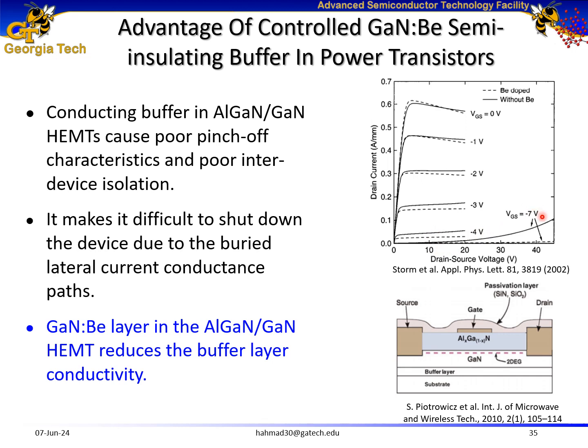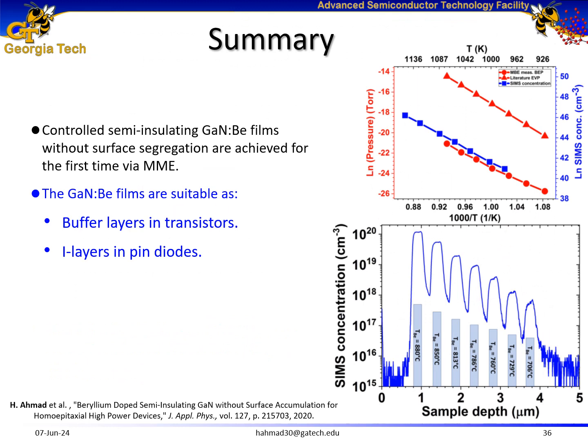Semi-insulating controlled beryllium-doped gallium nitride films are suitable to be used as buffer layers in transistors because conducting buffer layers would result in poor pinch-off characteristics. On the other hand, controlled semi-insulating films would improve the pinch-off characteristics of transistors. To summarize the key results, I achieved controlled semi-insulating beryllium-doped gallium nitride films without surface segregation for the first time. These films have the potential to be used as buffer layers in transistors and also as I layers in pin diodes.